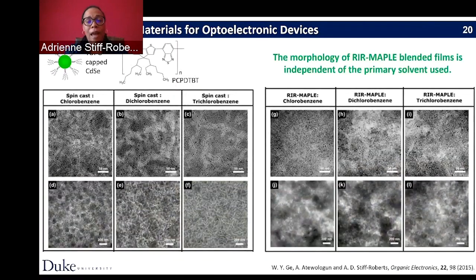Another demonstration that gets back to the goal of making hybrid materials is showing inorganic nanoparticles embedded in a polymer, which is where I started, how I got into this area, because those are the types of films that I wanted to make. In this case, these materials weren't chosen for an infrared photodetector, but for organic solar cells. And the interesting thing to note, again, is evidence that with MAPLE you're able to supersede the impact of solvent, and have the blending and the morphology of the film be determined by the laser deposition process.